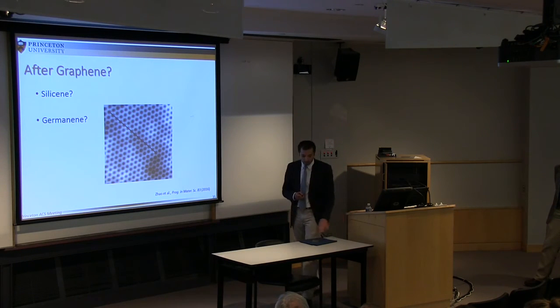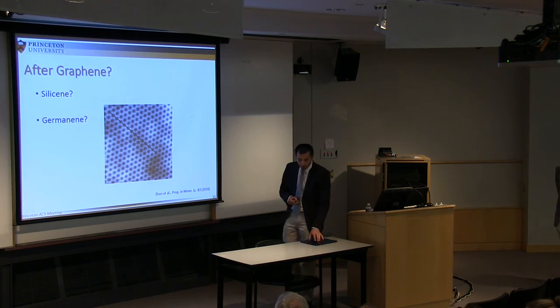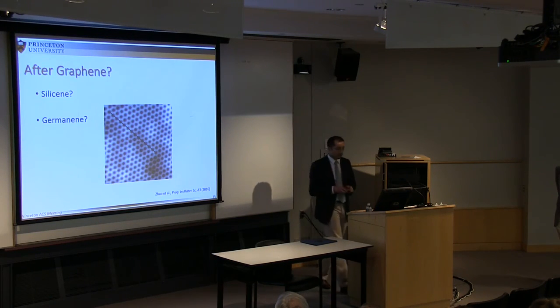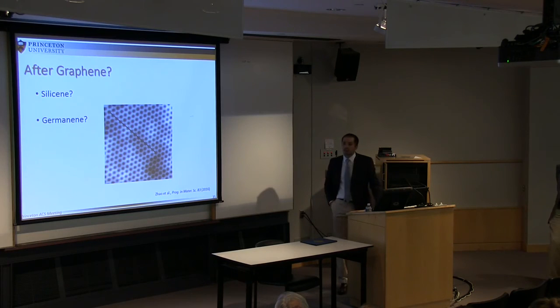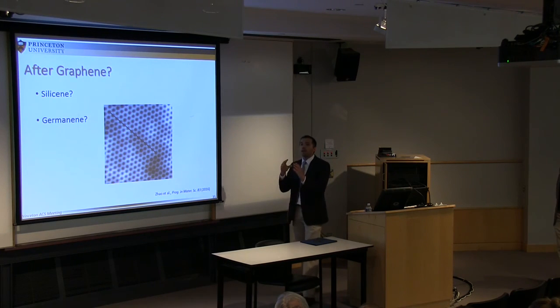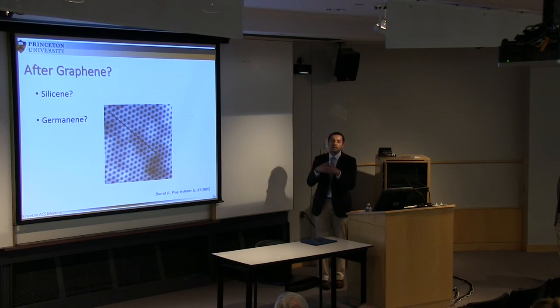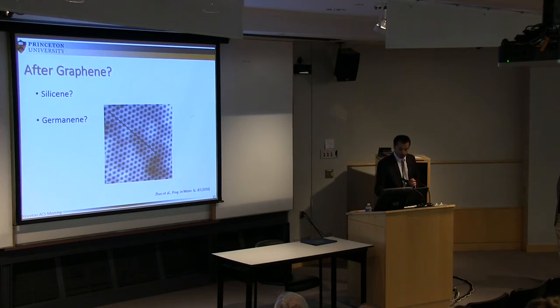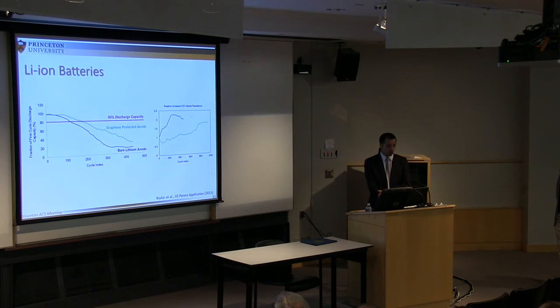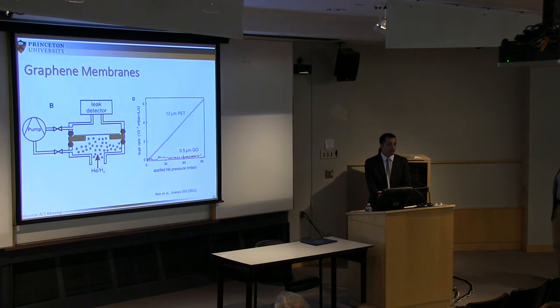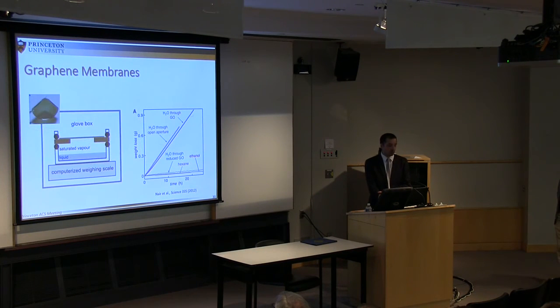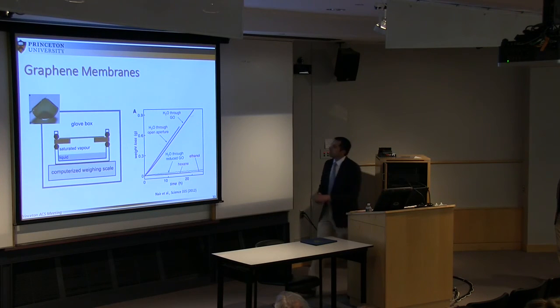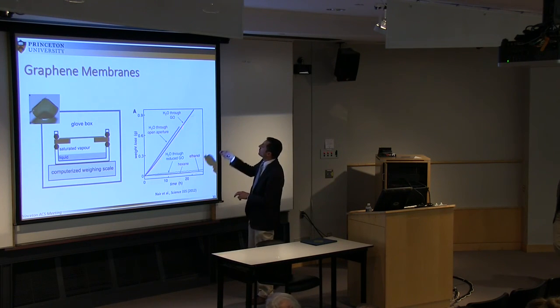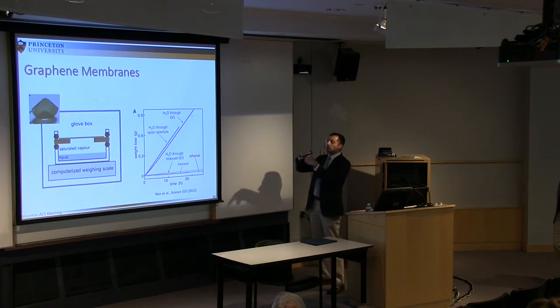So to respond to Forrest's question, let me clarify if I didn't answer properly. When we have a membrane, clearly we don't have a single sheet. We have multiple sheets on top of each other. In one case, Geim's group used graphene oxide, which is the non-reduced material. So when you don't reduce it, you just use it with the functional groups, so you have layers of graphene, and in between you have a small separation, with oxygen atoms.